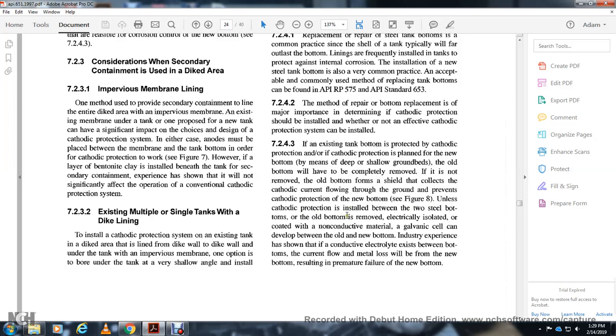If the old bottom is removed, electrically isolated with a non-conductive material, a galvanic cell can develop between the old and new bottom. Industrial experience has shown that with a conductive electrolyte between the bottoms, current flows and the metal left will be from the new bottom, resulting in premature failure of the new bottom.